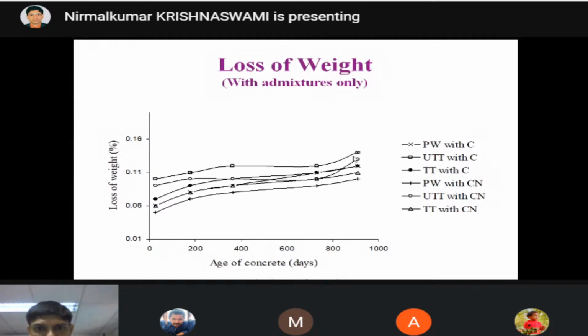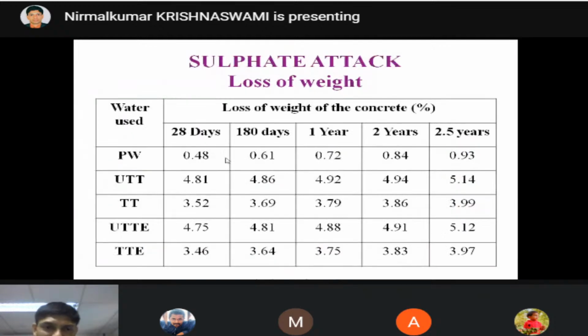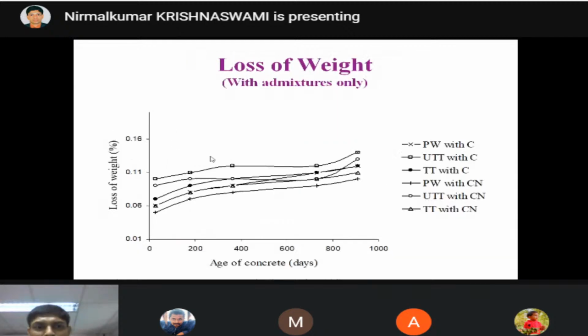If you see in the previous slide, even for potable water it is 0.48. But when we add the admixture, the loss of weight is less than 0.15 or 0.16 percent. So everything has been neutralized. All the loss of weight due to this sulfate attack has been neutralized.